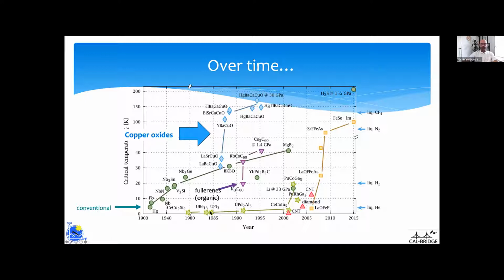It turns out that around the 80s comes this family called the copper oxides, which I'll explain in a little bit. You have all these materials that have very, very high transition temperatures. Then about 20 years later, there's another class of materials called iron-based superconductors, which also have high temperatures. And very recently, as in the last year, some people have discovered that under very high pressure, you can also get very high transition temperatures. So as you can see, the conventional theory has limitations, and it is necessary to come up with unconventional thinking to describe the materials that don't fit that model. Now, let me tell you why these materials are so weird.